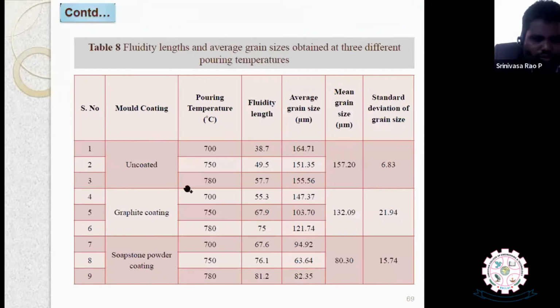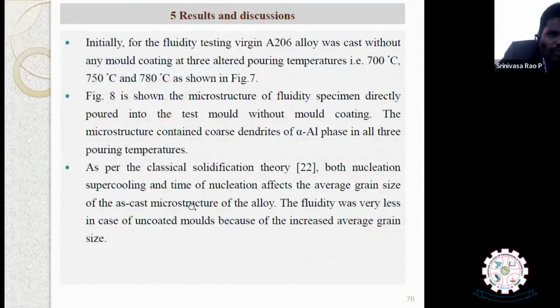First we did the casting without coating, that means uncoated, at 3 temperatures, 700, 750 and 780, then graphite coating at 700, 750, 780, and soapstone powder coating at 700, 750, 780. These are the pouring temperatures, and the fluidity length that we obtained at the different temperatures is this one. After this we studied the microstructure and found the average grain size, the mean grain size is this one, and this is the standard deviation.